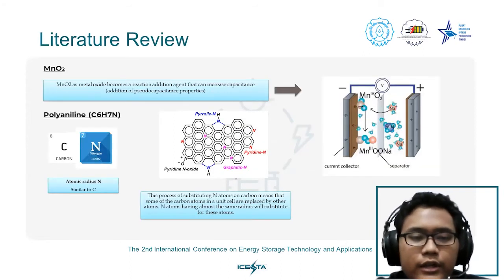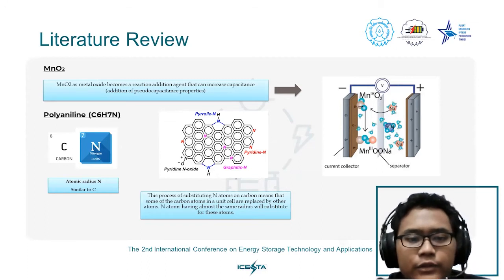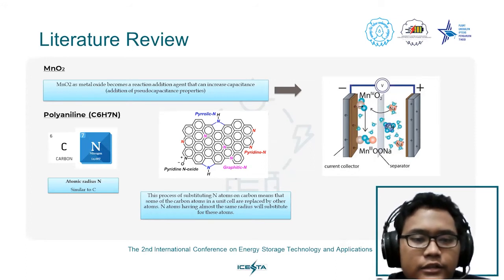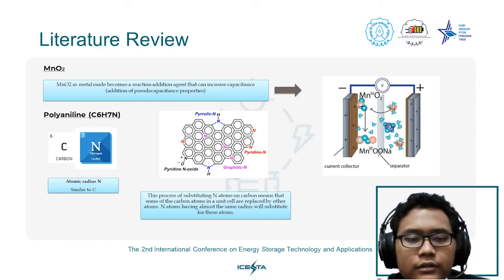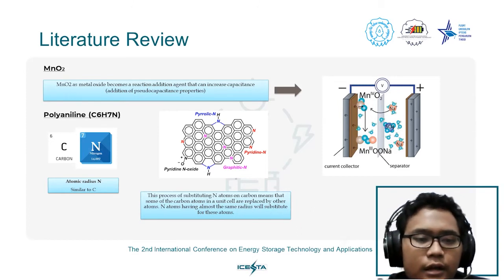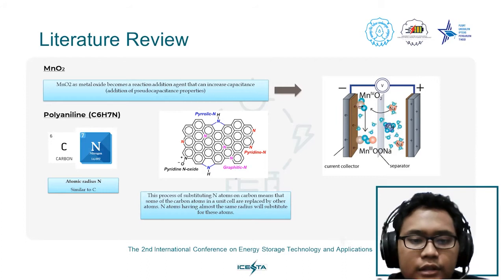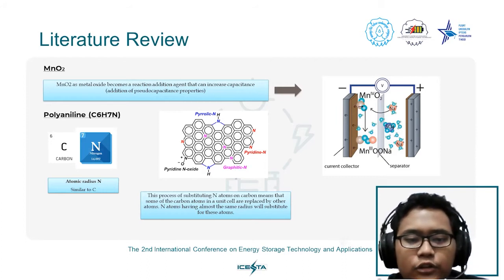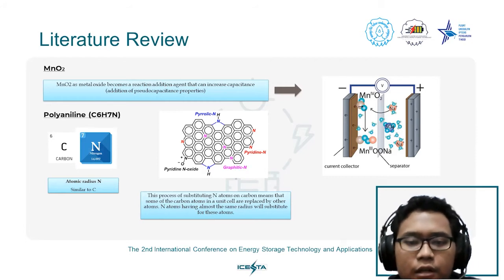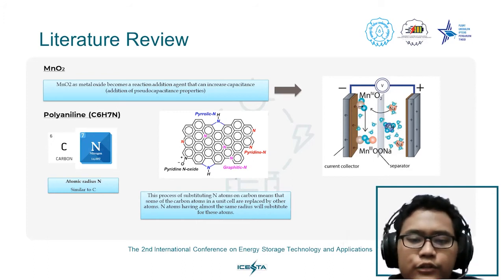And then manganese oxide. Manganese oxide, as a metal oxide, becomes an additional reaction that can increase capacitance, adding pseudo-capacitance properties to the supercapacitor. And then there is polyaniline. The atomic radius of the nitrogen atom is similar to that of the carbon atom. This process of substitution of nitrogen atoms on carbon means that some of the carbon atoms in a unit cell are replaced by nitrogen atoms, having an almost same radius as the substituted atom.